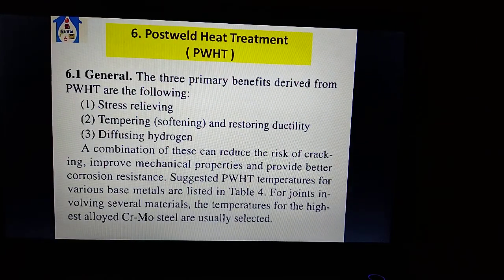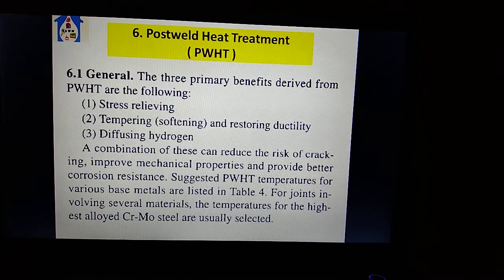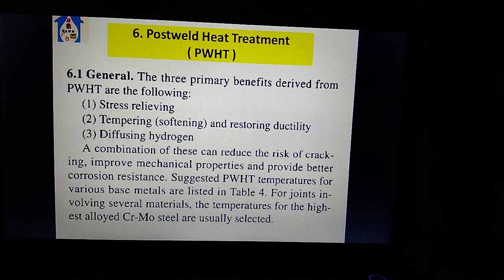Postweld Heat Treatment, PWHT. In general, the primary benefits derived from PWHT are the following. First, stress relieving. Second, tempering or softening and restoring ductility. Third, diffusing hydrogen. A combination of these can reduce the risks of cracking, improve mechanical properties, and provide better corrosion resistance. Suggested PWHT temperatures for various base metals are listed in Table 4. For joints involving several materials, the temperature for the highest alloyed chromium molybdenum steel is selected.